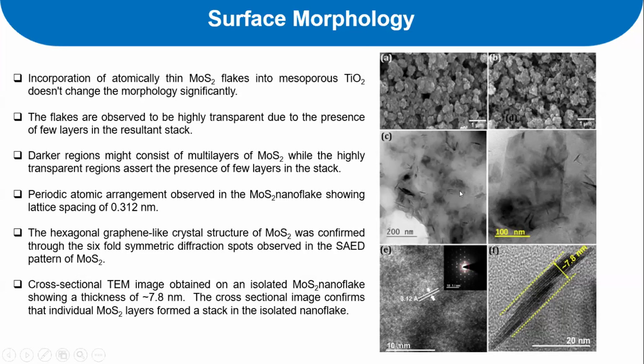They show extremely thin, transparent layers, and we just want to make sure that we have coated this material. So we went for transmission electron microscope studies, and we have studied the lattice image also. We have come to the conclusion that we got some 7.8 nanometer layers coated on the electron acceptors. We can clearly see we have taken an individual flake and observed that a 7.8 nanometer layer is floating on that structure. So it has been characterized showing those layers.